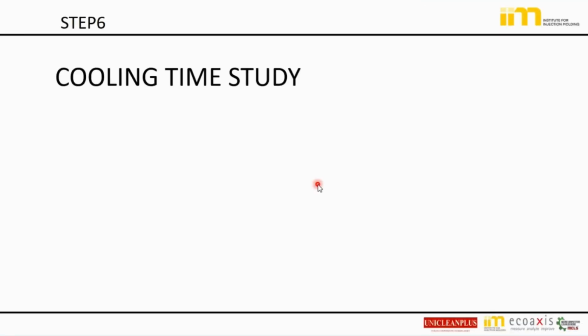Then is the cooling time study. Cooling time, as I told, is 60% of the cycle time. So if you want to save money, there is more saving in cooling. It's not just adjusting the cooling time in the machine. The mold should take care. It means there should be enough cooling lines in the mold. Looping should not be there. The mold is a thermal system, and proper thermal conduction should be there. If I tell you, there is no upper limit to the cooling lines.